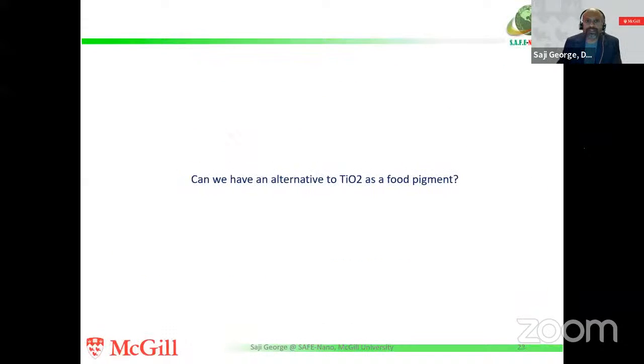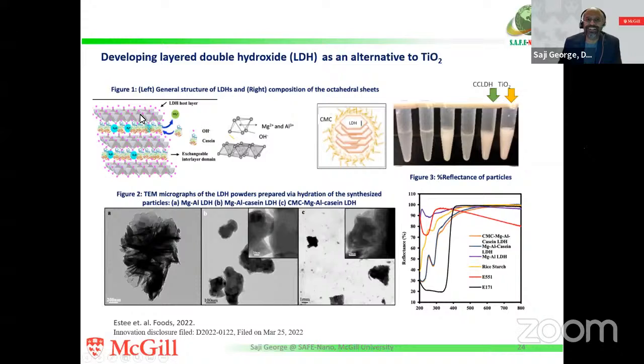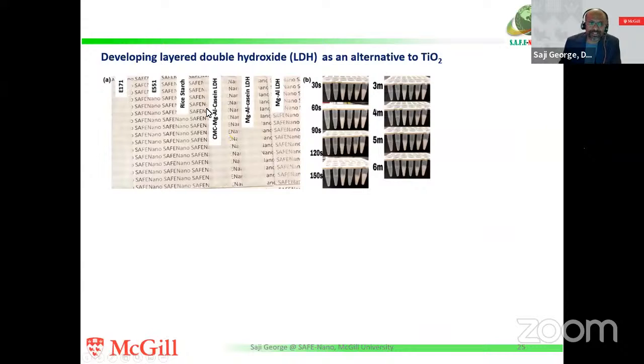Like I said, we are talking about sustainable nanotechnology applications as well. So we also looked into the possibility of creating something alternative to titanium dioxide. And here is an example showing that we created a composite material containing layered double hydroxide, which is a synthetic clay, where we intercalated it with proteins and then polymers of carbohydrate, and you can see they have a good masking power. They are not as good as titanium dioxide, but they are superior in performance in comparison to many of the other commercially available alternatives. And we show that it has a good masking power.